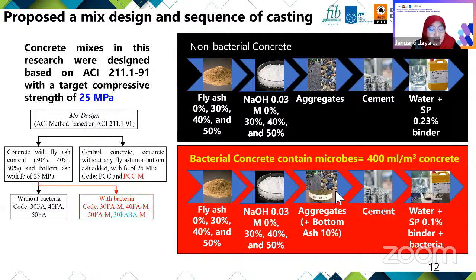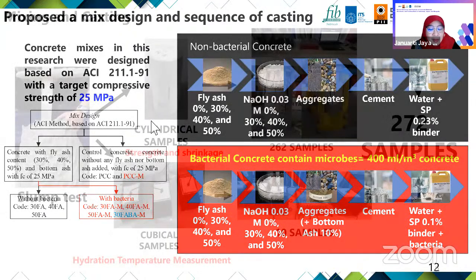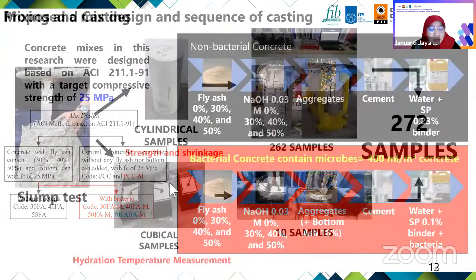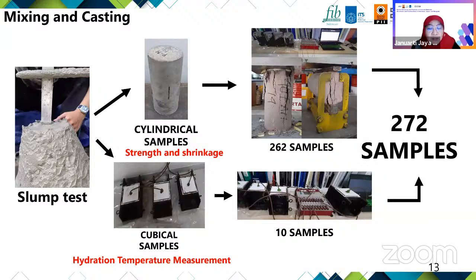And we made cylindrical specimens for the strength test and the shrinkage test. We also prepared cubical specimens for monitoring the hydration temperature in 24 hours after casting. In total, we have 272 specimens, and this is the result.